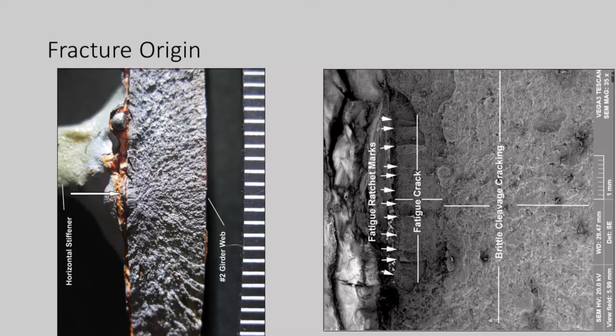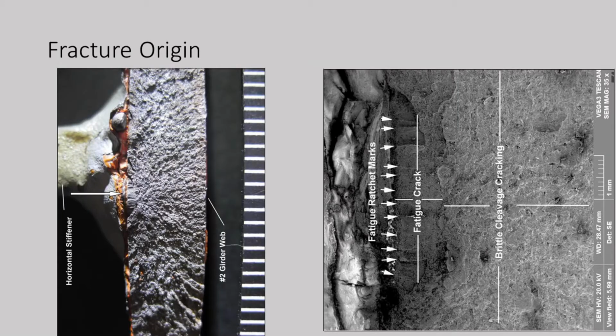And this is what you see at about 35 power magnification. In this area here in the picture, you see this grainy area that's got what he calls brittle cleavage cracking, which meant that the crack was running in that area. In this little thumbnail, he says, is a fatigue failure. And he says also you have these little marks along here. He calls those ratchet marks for major stops and starts in the crack as it moves.